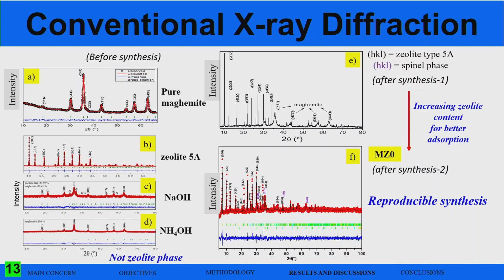And we use, in the co-precipitation method, sodium hydroxide and ammonium hydroxide in order to produce magnetic nanoparticles in the presence of zeolite. As we can see here, using sodium hydroxide, we obtain goethite and maghemite, a mixture. And using ammonium, here we see that we have only one phase. So it's really important, but the zeolite phase disappeared. The main peak here is not detected. So what we do after the synthesis is to produce a mechanical mixture under magnetic stirring for 24 hours, and we obtained the composite here of the maghemite and zeolite nanoparticles.